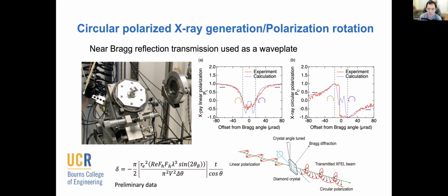As you can see here, this is our measurement of the beam using two detectors. One is placed horizontally off the beam, the other is placed vertically off the beam. We were able to reconstruct the linear component and the circularly polarized component of the beam after the beam passes through this polarizer. The dashed lines are our model, and the red lines are our measurement. You see that the agreement is pretty good.